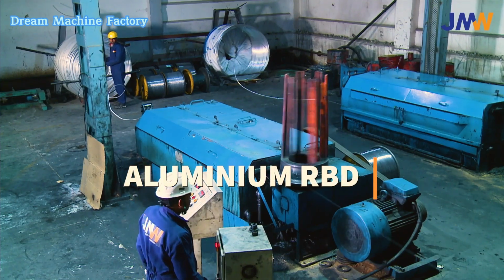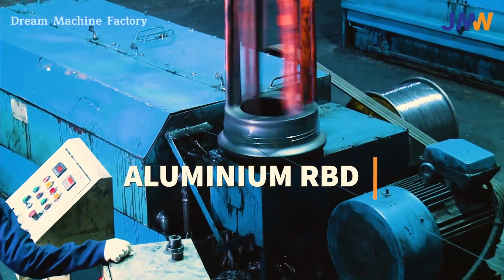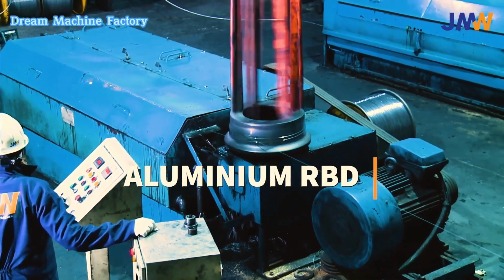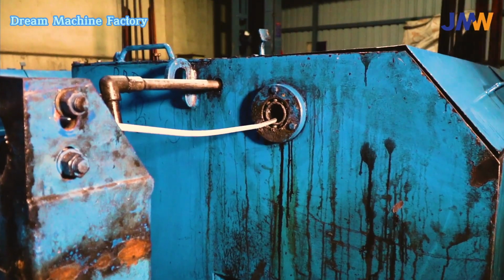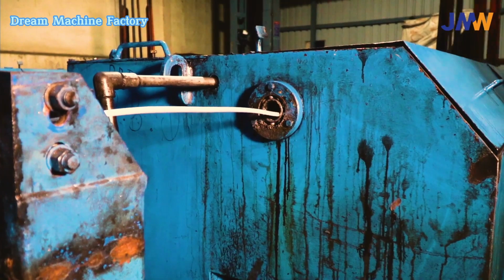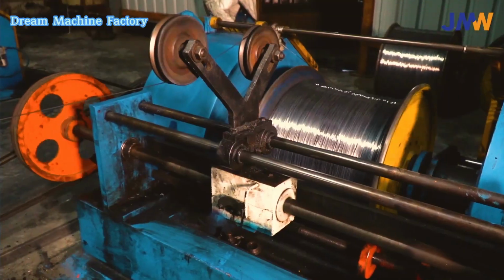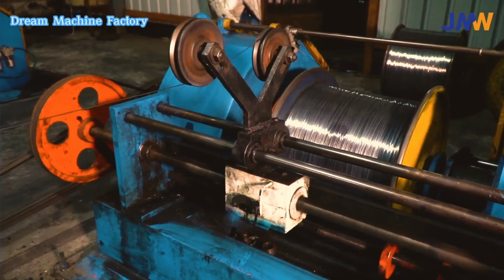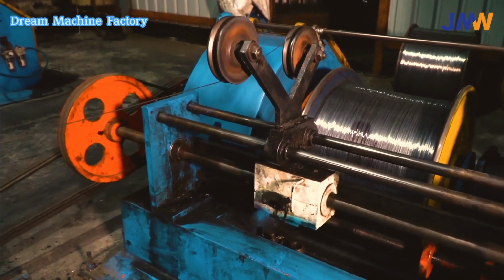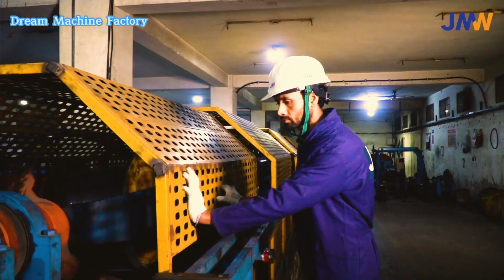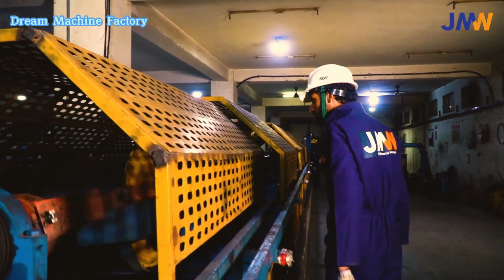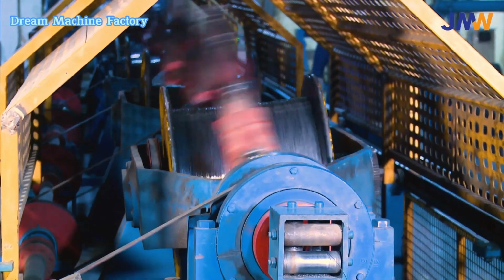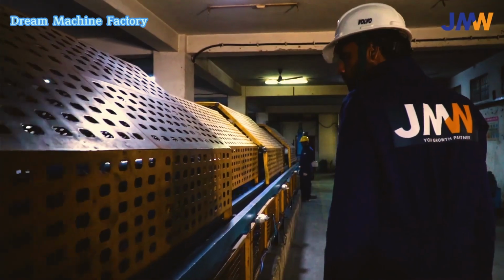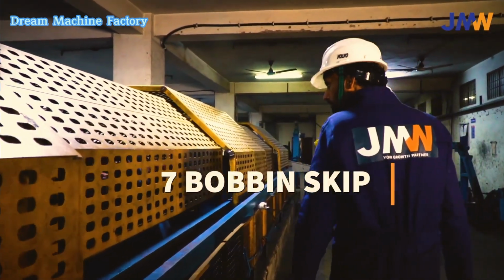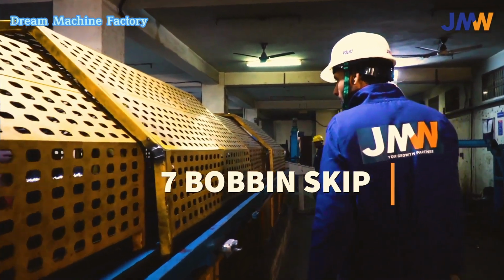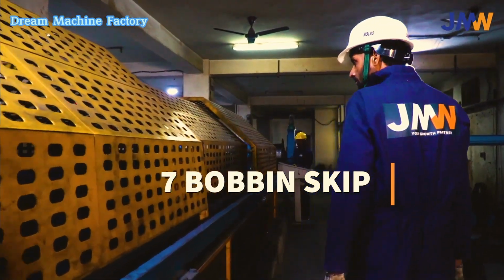The aluminum RBD rod breakdown process is used to convert large diameter aluminum rods, typically 9.5 mm, into smaller wire sizes suitable for electrical applications. The rod is drawn through a series of tungsten carbide or diamond dies using a multi-stage wire drawing machine, progressively reducing its diameter while increasing length and tensile strength. To prevent wire breakage and ensure surface quality, lubricants are applied during the process. After drawing, the wire may undergo annealing to restore ductility. RBD aluminum wire is commonly used in power transmission lines, cables, and electrical wiring due to its lightweight and good conductivity.